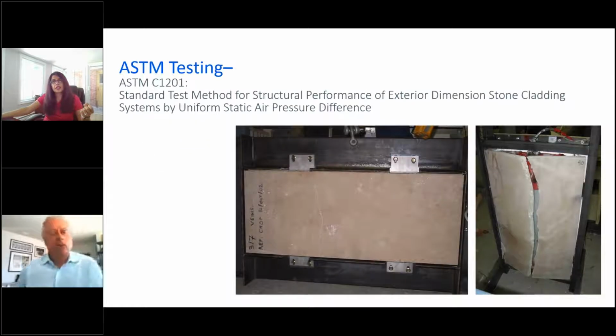The ASTM C1201 test is a full panel test, and this one is used in some applications where we want to test the actual assembly that we're proposing for the job. So you're getting the information from the flexural strength of the stone, you're getting the information from the anchors. You assemble a full-scale panel with an airbag put in behind it to simulate wind pressure on it, and you load the panel up. And what it will do is it'll demonstrate the mode of failure. We'll take it up to whatever load it fails at, and again, it's another measure of the safety factor for the entire assembly.